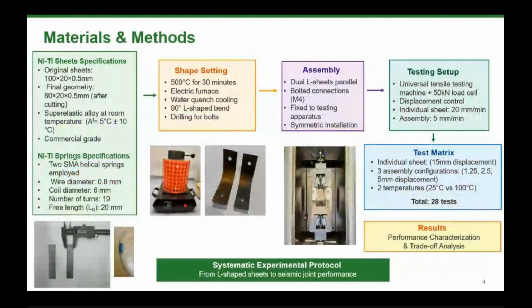So moving into detail in materials and methods, here you can find all the specifications of the materials used, that are sheets here and wires. And you can see in particular that we use the superelastic alloy at room temperature. The manufacturer said that they had an austenite finish of 5 degrees Celsius. So we are sure that they are superelastic at room temperature. And then the shape memory alloy sheets and springs underwent a shape setting treatment in a furnace. That is this one, the furnace of the laboratory, at 500 degrees Celsius for 30 minutes.